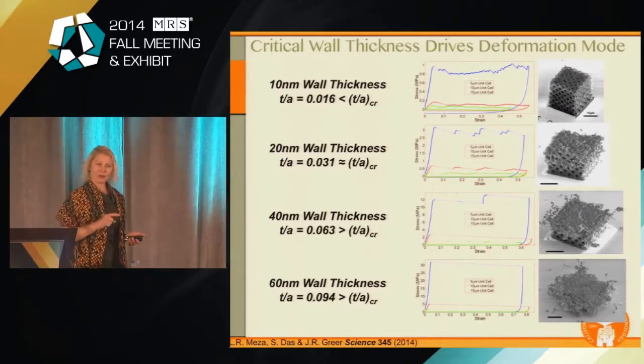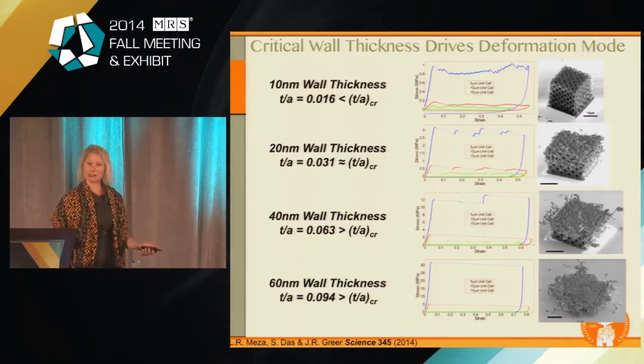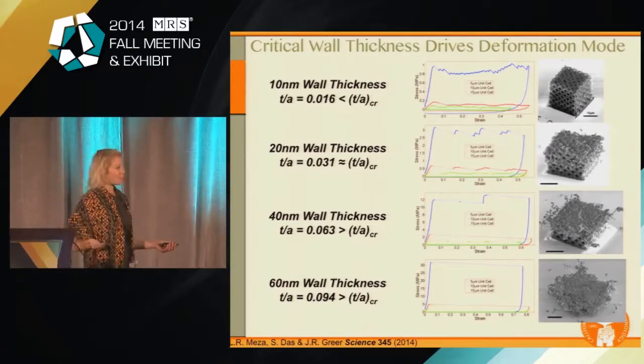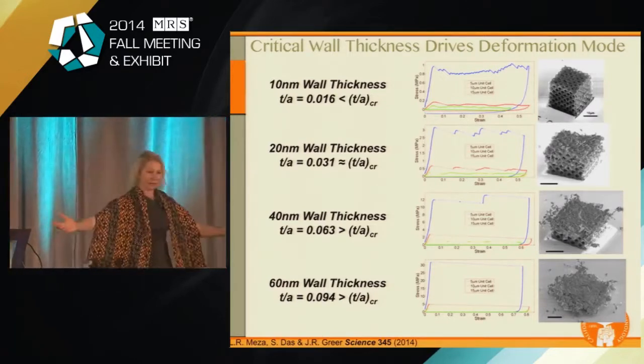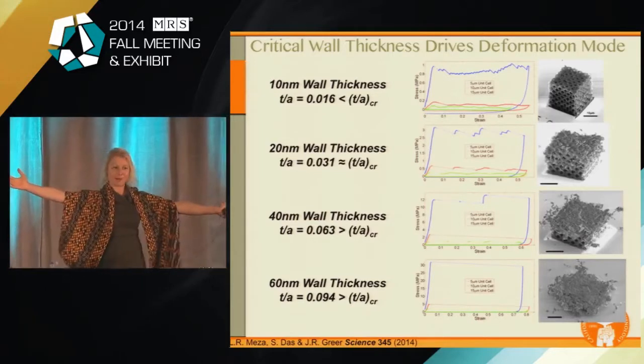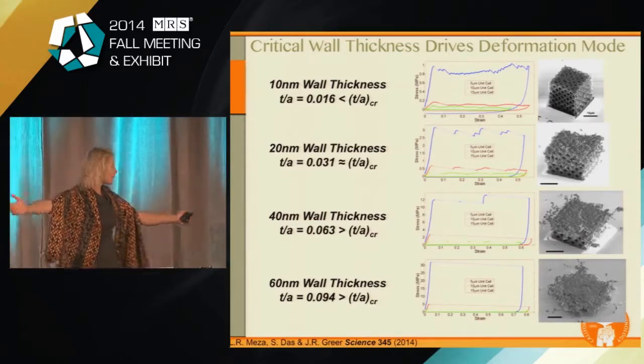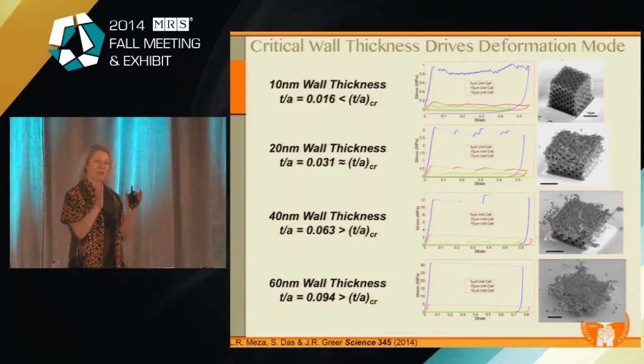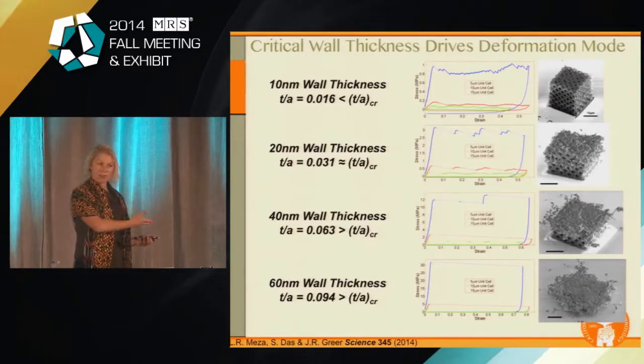Now, the question is, I told you it was all about the size effect, right? But this explanation is all mechanistic. It's all about the ratio, T over A. Well, if it's all about the ratio, T over A, that means that it's scale-free, right? That means that we should be able to scale this thing up to about 10 kilometers by 10 kilometers by 10 kilometers, such that the wall thickness becomes 10 centimeters, if we scale it up in a self-similar way. And then we should expect exactly the same behavior, at least based on this theory.